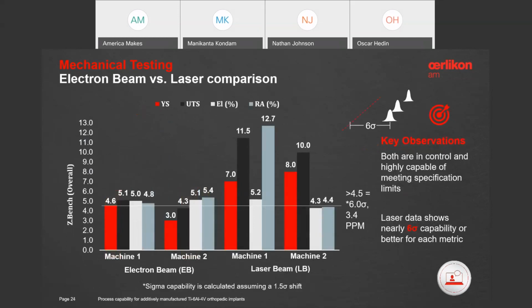So in comparison between EBM and laser beam, just to be clear, our aim here is not to endorse one technology over the other. The goal here is to prove, irrespective of the technology used, we are able to achieve a Six Sigma level process. We do see on EBM, on machine 2, where we have a lower z-score on the yield strength, but that does not mean that the process is not capable of achieving the specification limits. There is additional work to be done and more controls to be included, but the process is nearly performing at Six Sigma for every machine we analyzed. However, as a side note, the laser data definitely shows a nearly Six Sigma process and very similar results from one machine to the other.